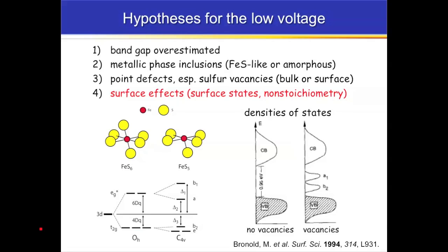If you pull sulfur off of one of the iron centers, normally they're octahedrally coordinated. If you pull a sulfur off, you're going to drop a molecular orbital into the band gap from the conduction band and promote one from the valence band. And so you can contaminate the band gap with these additional states. This, in principle, could lead to a low voltage because effectively you're going to have a lower band gap material if you do that. And then idea number 4 here, and this is the one that we've done the most